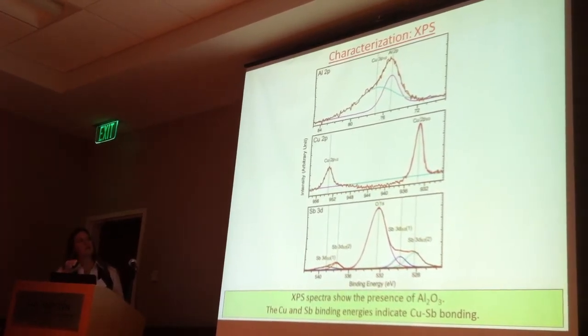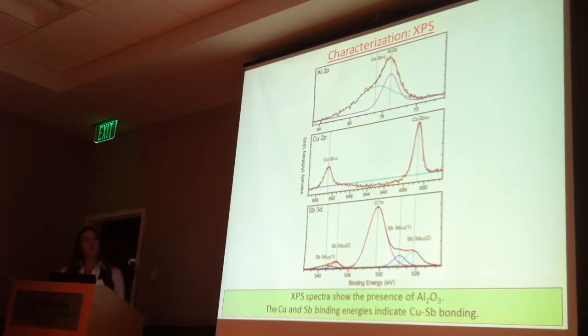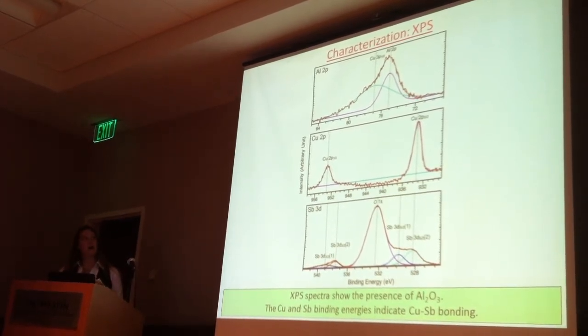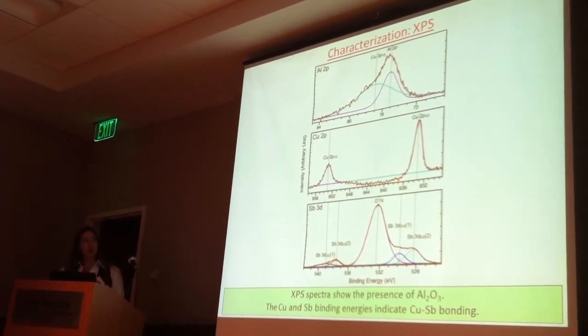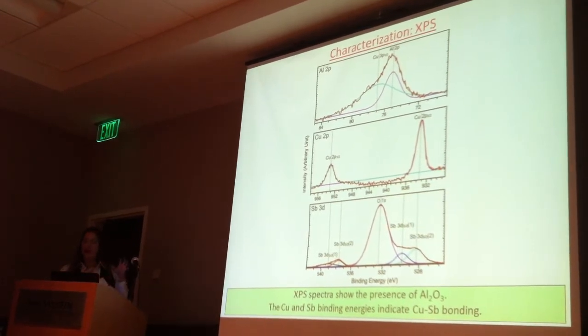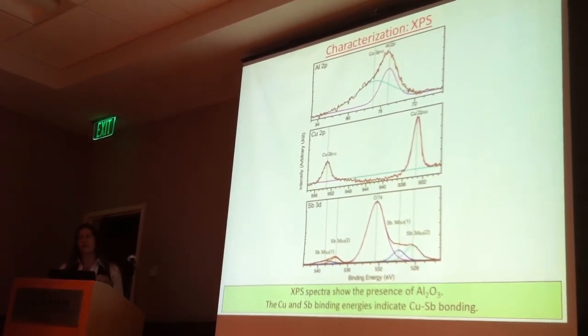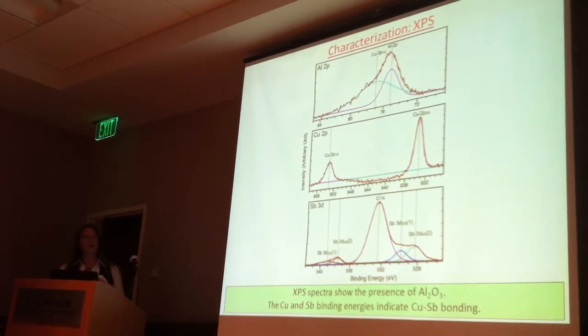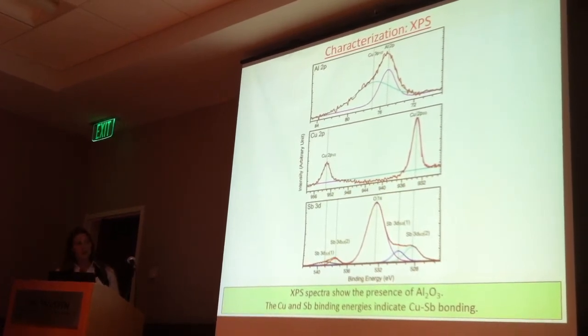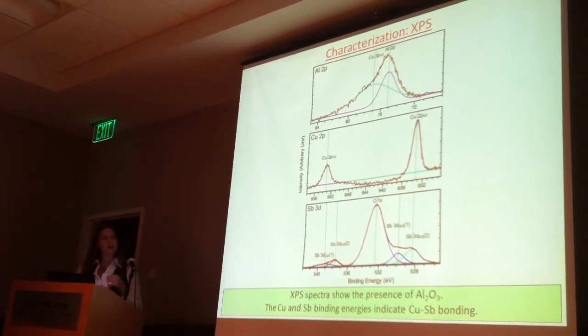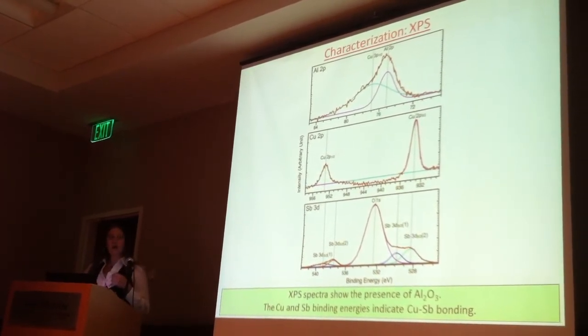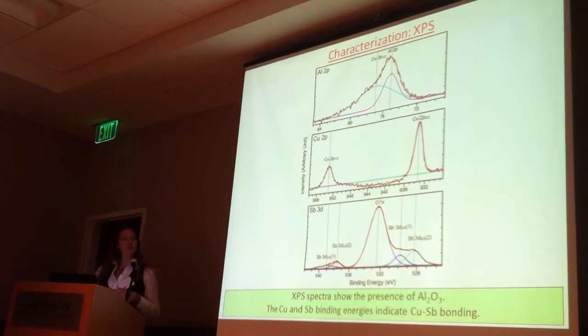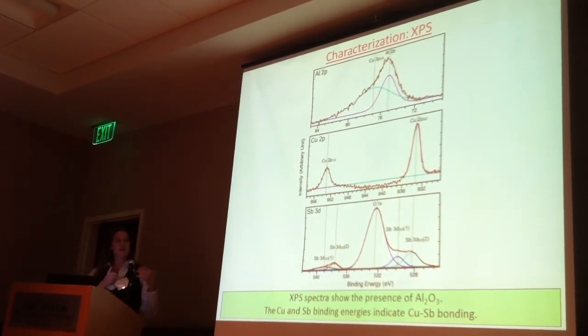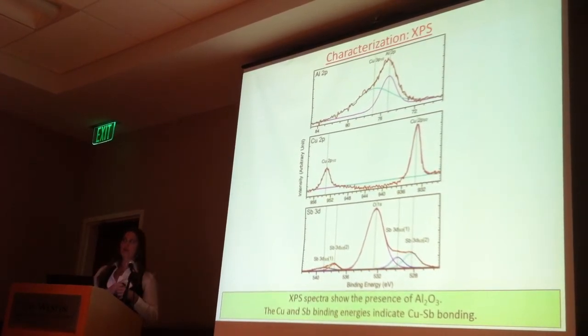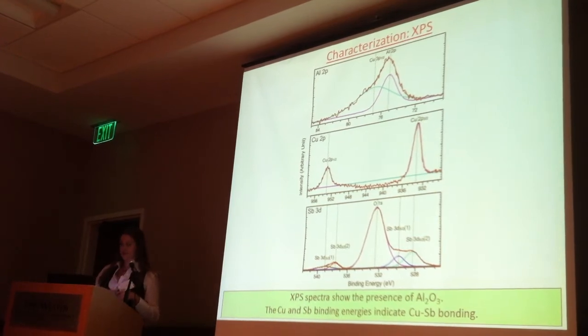Copper oxide sort of has several different peaks. So we found that we didn't have copper oxide, and we also had copper peaks that were shifted to higher binding energies, indicating that they had been bound to something. It's not metallic copper. One other thing that we found when we looked at the antimony spectrum for XPS is that we had a small amount of metallic antimony impurity. So we have antimony that is bonded to something, and we also have a small amount of metallic antimony.